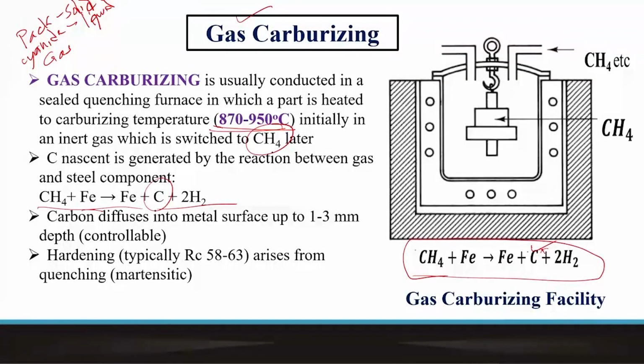surface. So this component which is suspended in a gaseous environment, here again we have a sealed furnace because we are dealing with methane, and of course release of methane to the atmosphere is not as dangerous as cyanide, but nevertheless we want to retain a certain concentration or potential of carbon enrichment inside the chamber. So this charge is suspended from the top and the lid is closed. We charge methane and methane hydrogen or a certain mixture, and then we heat.